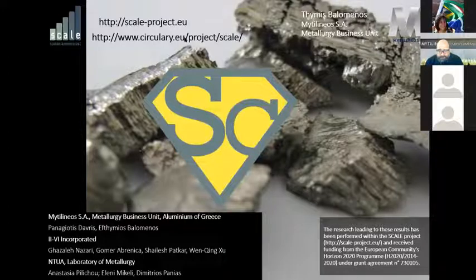And there have been previous studies like the one I showed with the ionic liquids, where indeed you could co-extract the rare earths after the scandium extraction. So again, scandium separates itself from the solution. It's easy to precipitate out scandium and leave the rest of the rare earths inside. So it's a fairly easy separation. In the case which I just detailed with the sulfuric acid, we are losing the rare earths inside the gypsum we're forming, right? If we wanted to pick up the rare earths as well, we should go for hydrochloric acid leaching, which would allow us not to precipitate the rare earths as double salts with the sulfuric acid.